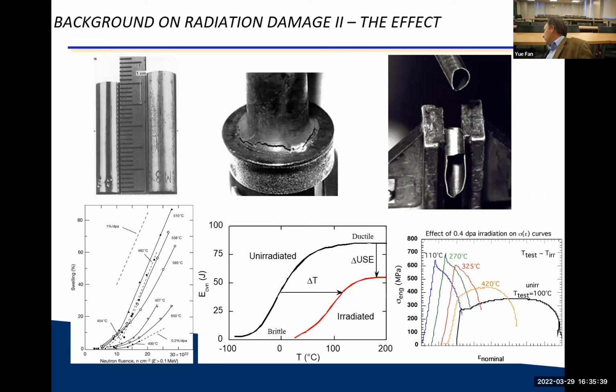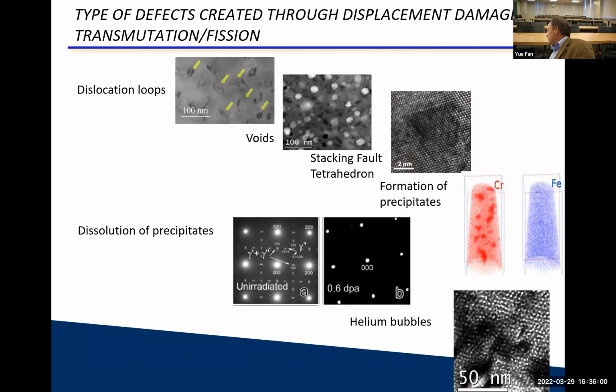And of course, the resulting data is where you have a shift in ductile to brittle transition temperature. That can be problematic, or an increase in yield strength, but a decrease in uniform and total elongation, which of course means this material behaves rather brittle. So those are the effects of this. And the cause of this, as I mentioned, are loops, voids, stacking fault tetrahedra, precipitates. Sometimes you can also get the dissolution of precipitates. So when you have strengthening phases like gamma prime, gamma double prime phases, when they get irradiated, they can disappear under dose. So you can actually shoot them back in solution. So you can actually have both. You can have the formation of precipitates as well as the dissolution of precipitates.